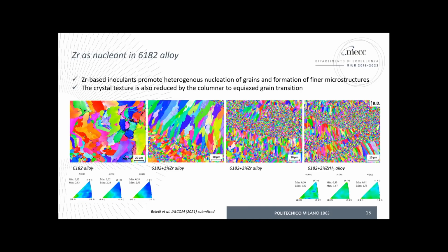I think here it's a question of having a good mixing, a good even distribution of zirconium in the volume of the liquid and then in the volume of the solid phase. But okay, in principle it works quite well. This is the same alloy with, let's say, the heterogeneous addition of zirconium dihydride particles that were added to the original powder. Again, they melt and they produce a quite similar microstructure.